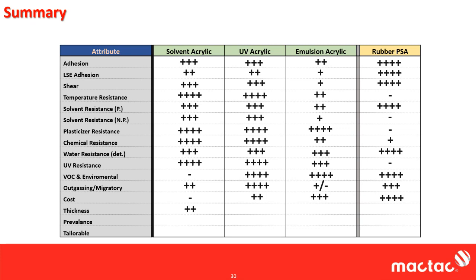Looking at the thicknesses you can achieve, up to about 5 mils of a solvent acrylic. It's about as high as you're going to get dried. UV acrylic, again, 15-20 mils is touted at the top end for some of the free radicals. Emulsion acrylic, you're only going to get 2, maybe 3 mils tops. And rubber PSAs, actually, as much as you can pump, you can coat. We coat up to 50 mils on rubber PSA.